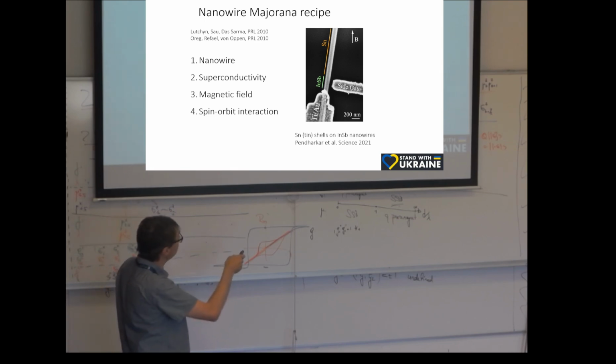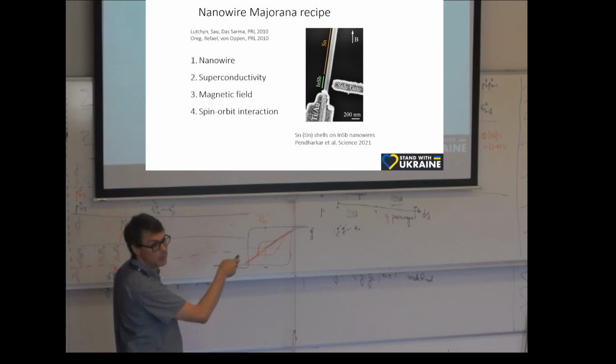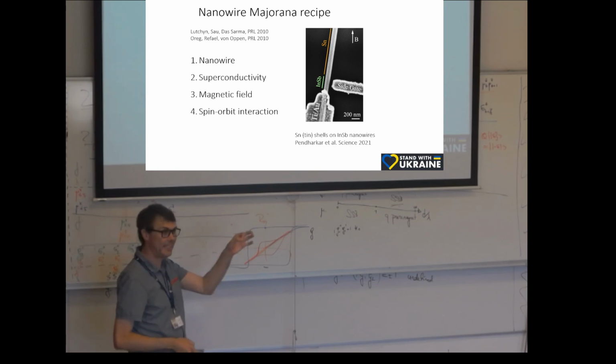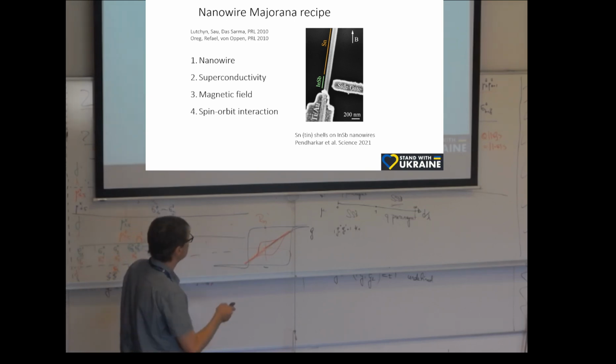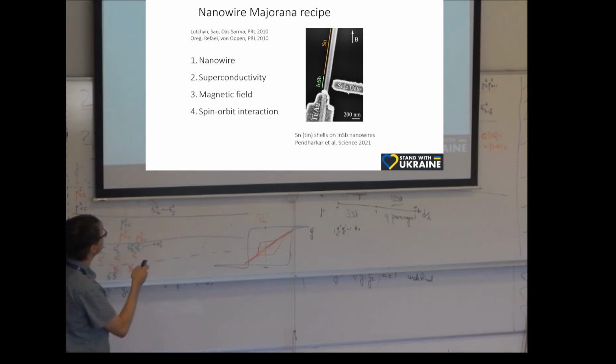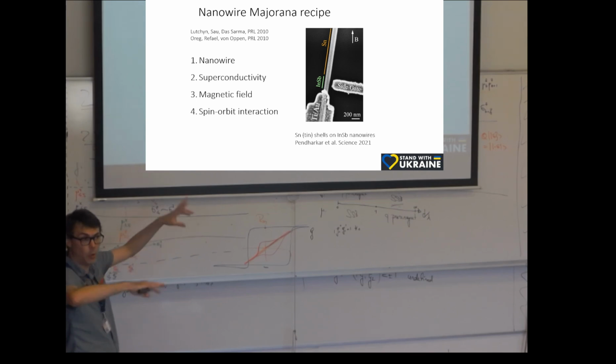And then in this particular sample, we also coated it with a very thin layer. You cannot see it, so it's marked by this line, and that's tin. It's a superconducting metal, goes superconducting at low temperature. And so this is sort of where you probe, the measurement is a tiny probe. But look at the ingredients. Nanowire, superconductivity induced by proximity, the proximity effect.